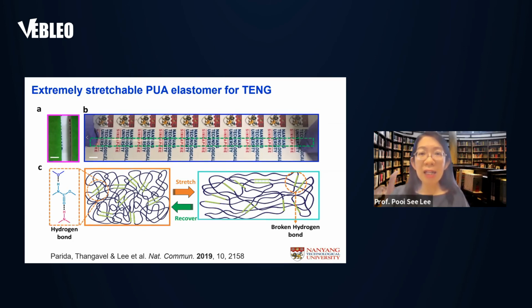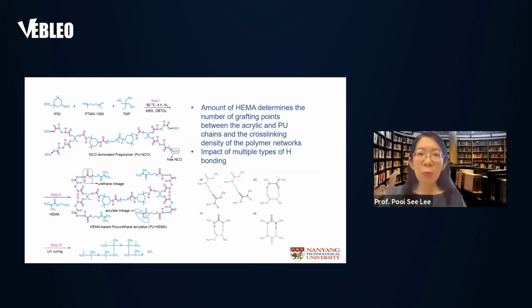An example is the highly stretchable triboelectric device as shown here, where preparation of an elastomer which can serve as a triboelectric active layer is very crucial. The hydrogen bonding in the polyurethane acrylate material, or elastomer, creates the possibility to do that. And we also introduced functional groups such as HEMA in order to tailor the cross-linking density and provide multiple types of hydrogen bonding in the polyurethane acrylate.